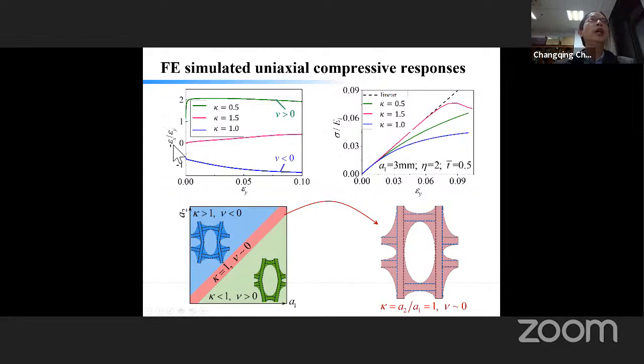This figure shows the strain response as a function of epsilon Y. Epsilon Y is the applied strain in the vertical direction, and epsilon X is the response strain in the transverse direction, in the X direction. So basically, minus epsilon X over epsilon Y is the Poisson's ratio. Now, if we look at different parameters, for kappa equal to 0.5, here is the green one, you have positive Poisson's ratio. For kappa equal to 1, the red one, you have almost zero Poisson's ratio. And the blue one is kappa equal to 1.5, where we have negative Poisson's ratio.